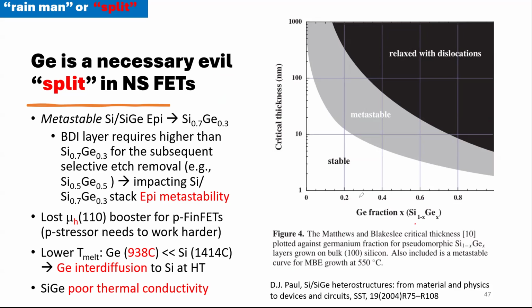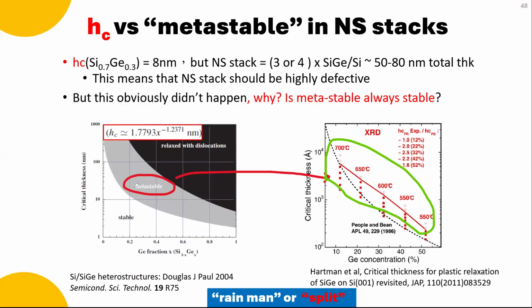We're doing nanosheet at 30% germanium here. But how thick could we put it in? If you do this, the theoretical most stable is like 8 nanometer. That's it. We'll show the calculation to you later. No, let me show you right now. Here, this line, somebody calculated 1.7793x power this. It's an empirical formula. 8 nanometer is 0.3. But your nanosheet stack is what? 3 or 4 nanosheets with silicon is a total of 50 to 80 nanometer total thickness for the nanosheet stack.